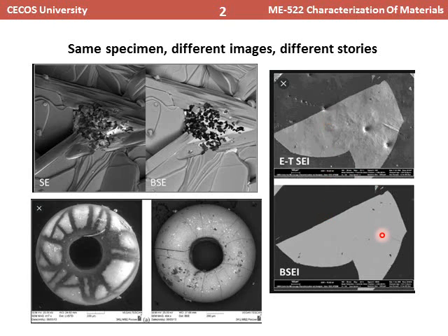But unfortunately, we lose the surface morphology features like these holes. In backscattered electron, we cannot see the surface topography or surface morphology in depth, but we can clearly observe the contrast of this artifact with respect to the base of the specimen.